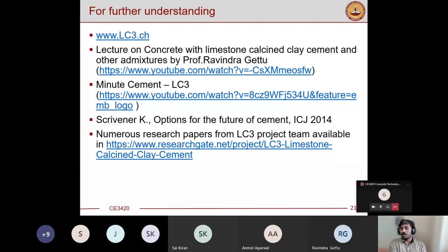The impure clay will be just available at the overlay. Nobody would use it in other industry. So the availability and usage of this clay is much more useful in cement-like application. So indirectly, it might be more expensive. But again, what you have said is it is not necessary to go for clays with very high purity. It looks like if you have kaolinite content of 50 to 60%, that is working better than the other cases. Exactly. Any other questions?